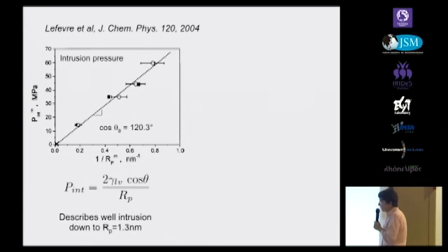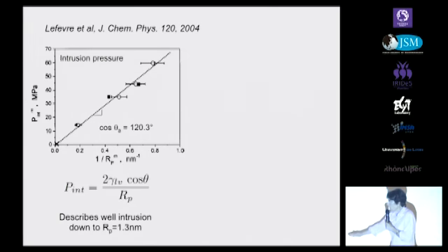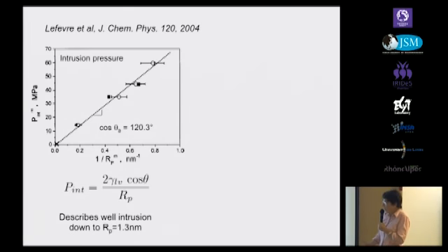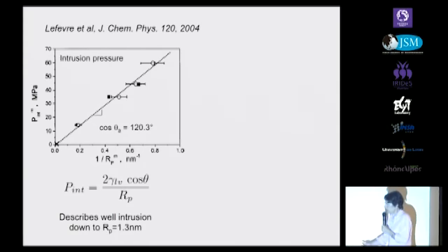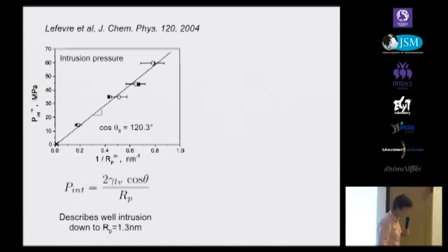This means that this quantitative law allows one to design porous materials able to meet a well-defined intrusion pressure by tuning the pore size of the material.